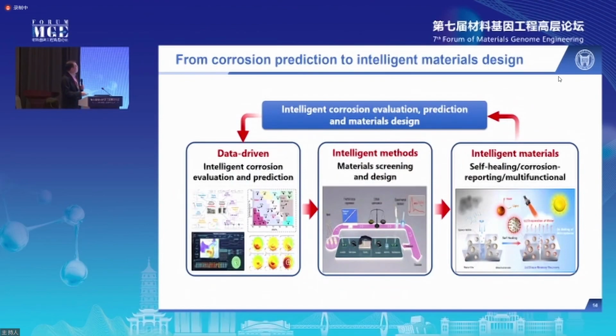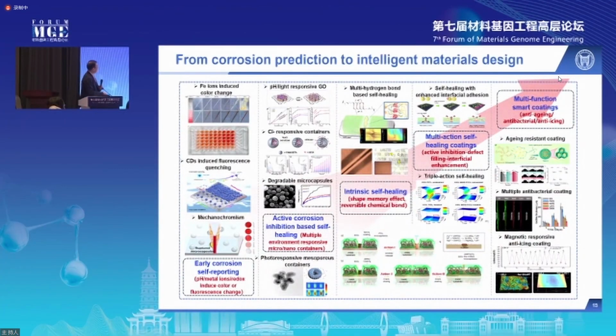So over the years, we have been not only using data-driven approaches for corrosion prediction, but also for more effective design and screening of materials, and particularly on intelligent materials, namely self-healing coatings, corrosion reporting coatings, or multifunctional coatings. And this is a general scheme summarizing what we have done in recent years on this intelligent coating, ranging from self-reporting coating that can detect early corrosion, and self-healing coating based on active corrosion inhibition, and also intrinsic self-healing coating based on reversible physical or chemical structures, and also multi-action self-healing coating that can consist of different kinds of self-healing mechanisms, and eventually multifunctional smart coating, for example, antibacterial, anti-icing.